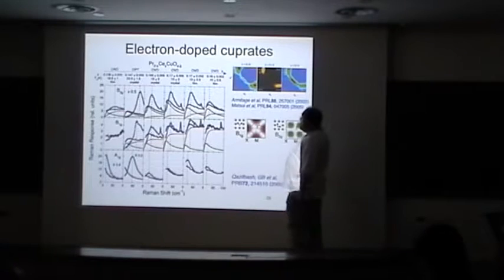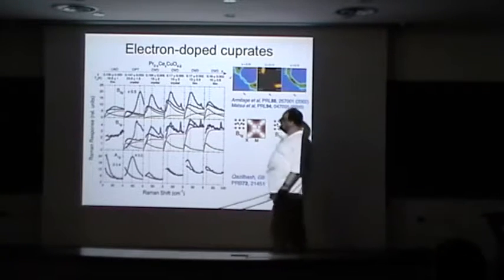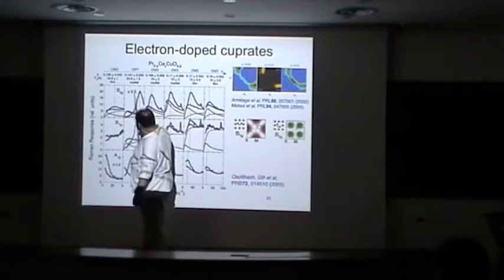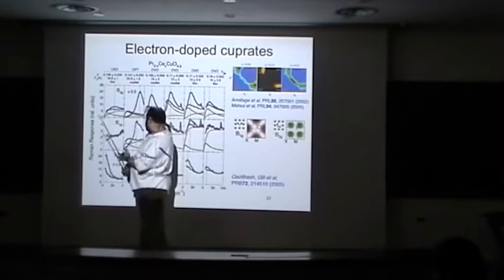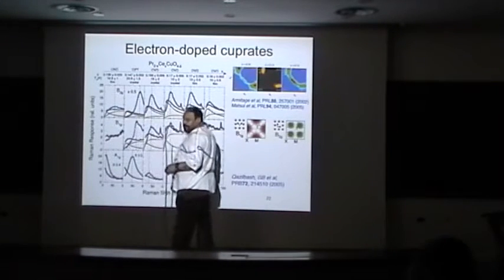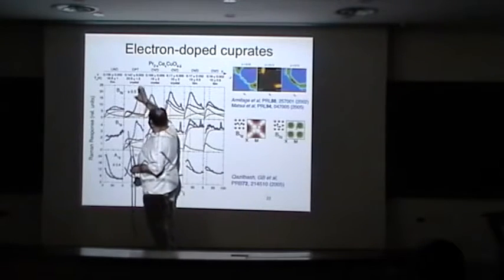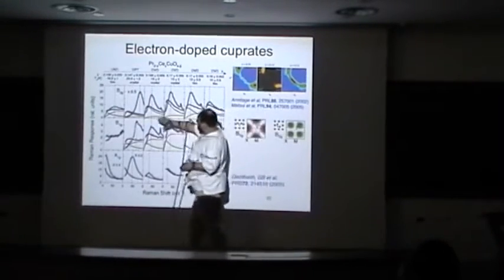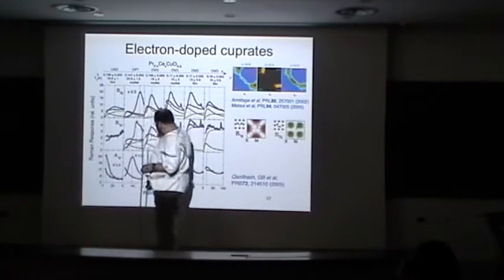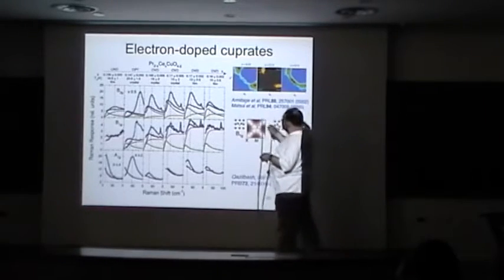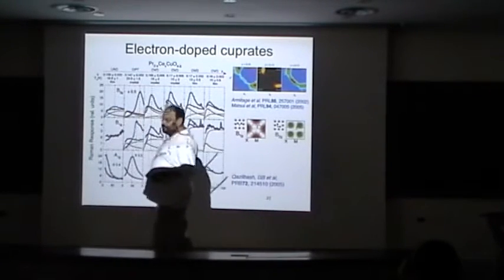And that can be directly seen from Raman scattering, where we can separate the contribution of the hole pocket and the electron pocket. And indeed, in very underdoped material, the Tc is low. There is almost no contribution from the electron pocket, and there is this pair breaking excitation, where the integral under that can tell us something about the Cooper pair density. Now when these pockets grow, we get a very healthy peak here. It's divided by 2, it doesn't fit in the scale. This is 25, so it goes all the way to 50, and this is the strongest feature there. So really the superconductivity in so-called electron doped compounds lives on these hole pockets, so they're actually hole type superconductors.